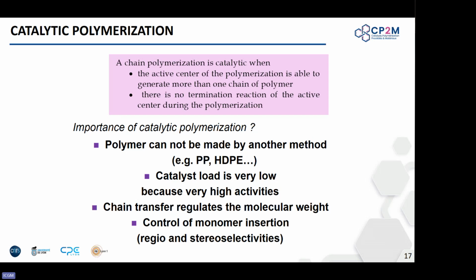There are many polymers that cannot really be made by another strategy. Okay, so in the case of PP, if you don't have a catalyst, isotactic PP is out of the question. Okay, HDPE is very similar. You need a metal catalyst for that, and you want the catalyst to be very, very low in amount. You want very high activity because of productivity reasons, but also because the catalyst will be embedded in your polymer. You cannot really remove it in the end, especially in these semi-crystalline polymers. And there are some chain transfer reactions that can control this. I talked a little bit about hydrogen. Hydrogen is a very good chain transfer agent, so you can mitigate the molar masses this way.